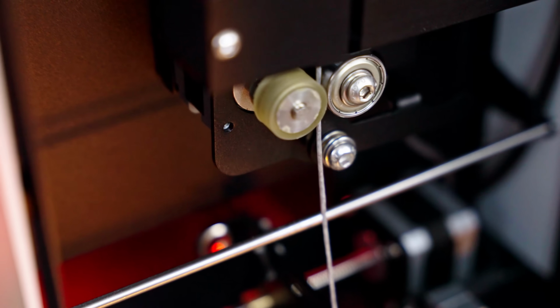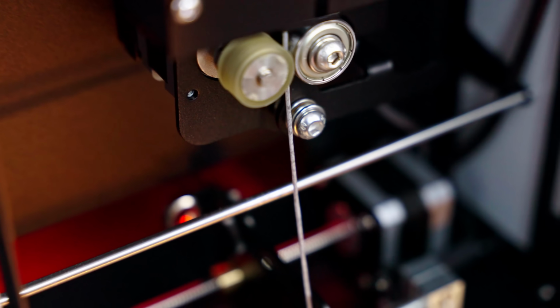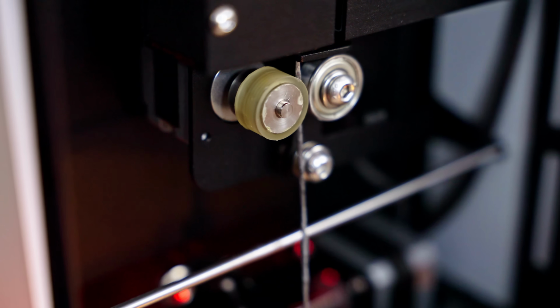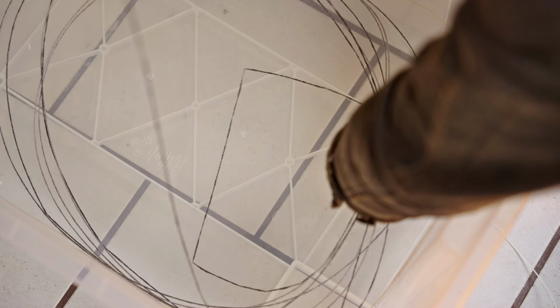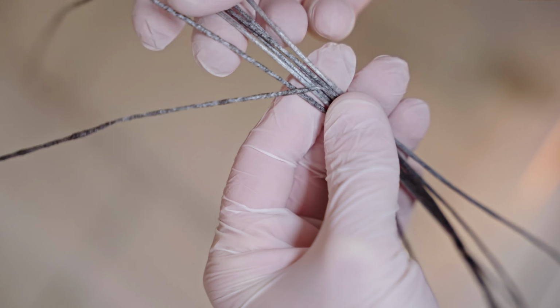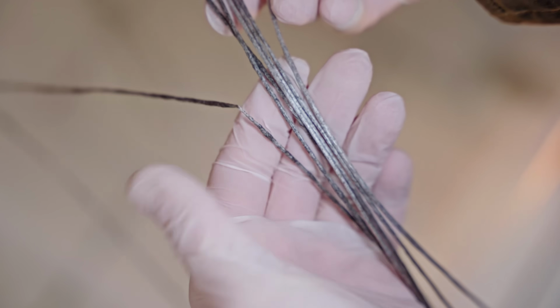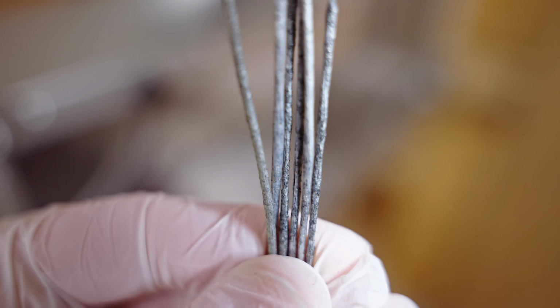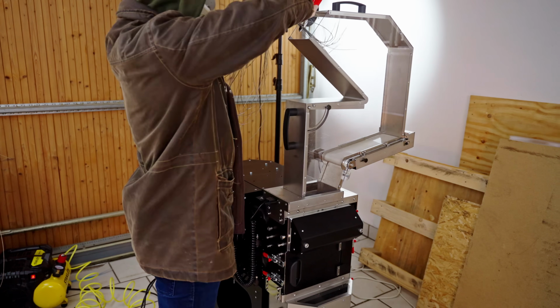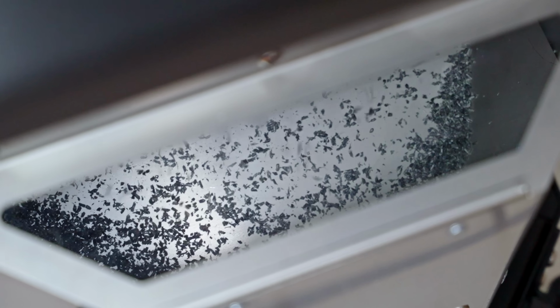Now, once we got to the carbon fiber mix with the particles in the right size range and about 15% by weight, you could clearly see that the extrude wasn't going well. Thankfully though, I still have the shredder around, so I can just let this batch finish and basically use that as a pre-mixing stage. All I have to do then is to roughly chop up the filament, and the shredder is going to turn it back into granulates.